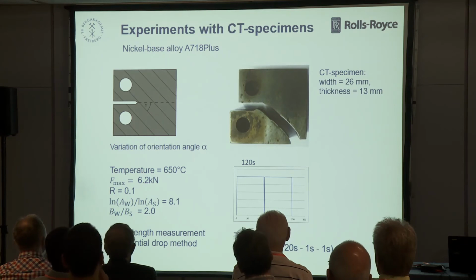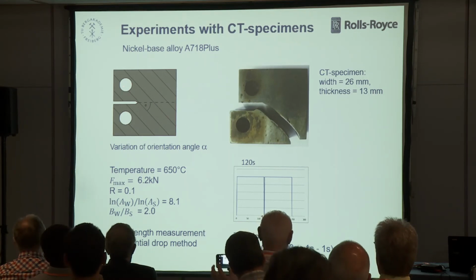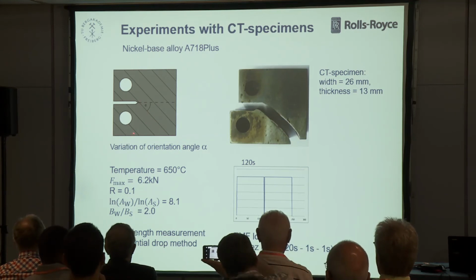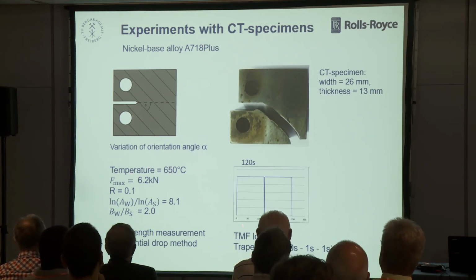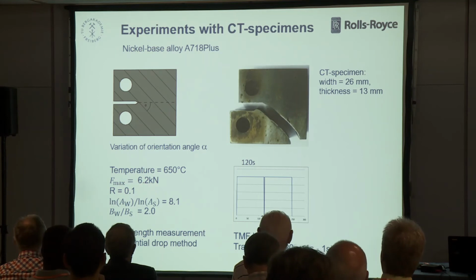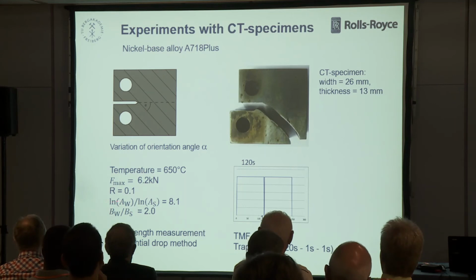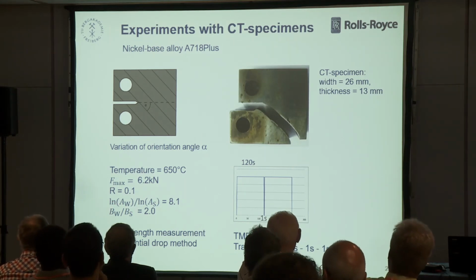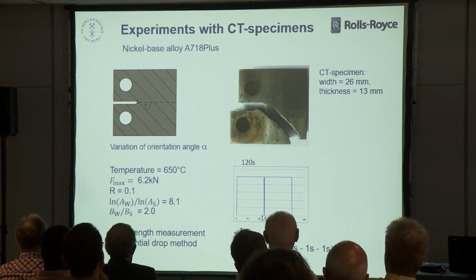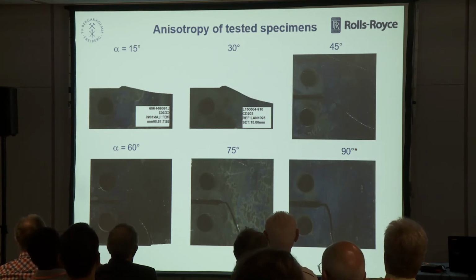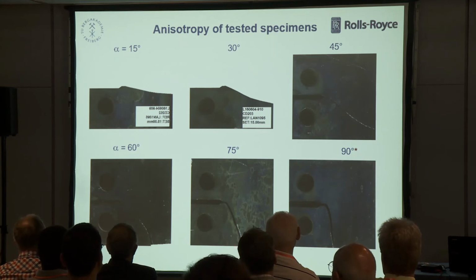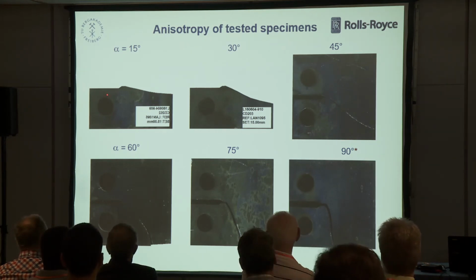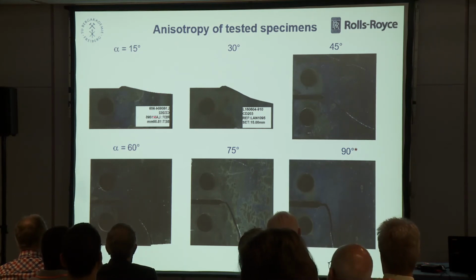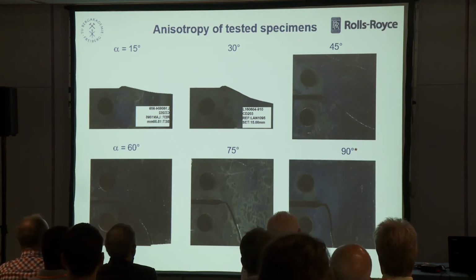Now let's come to the experiments. So Rolls-Royce conducted experiments where they cut CT specimens out from this forged piece in different orientations, alignments with different angles, alpha, with respect to the crack. And these were TMF experiments, 650 degrees up and down, and R ratio of 0.1. And from the corner crack specimens, we have the parameters of A and B for the two extreme directions. Length was measured with a potential drop method. So here you see the results for different inclination angles: 15 degree, 30 degree, 45 degree, 60 degree, 75 degree, and 90 degree. So the crack turns a little bit, but parallel to the alignment of the precipitates, and finally it follows it. So it's really a strange effect.